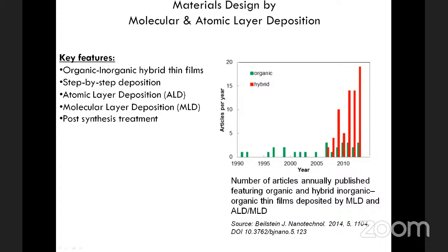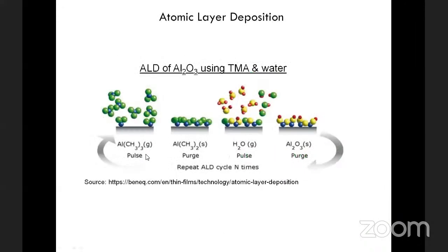Atomic and molecular layer deposition allows a step-by-step deposition at the atomic and molecular levels, respectively, of thin films, while controlling the composition and details of the thin films deposited. Probably most of you have some background and are aware, but I'll just give a very brief introduction. So this is a typical synthesis of aluminum oxide using atomic layer deposition by trimethyl aluminum and water.